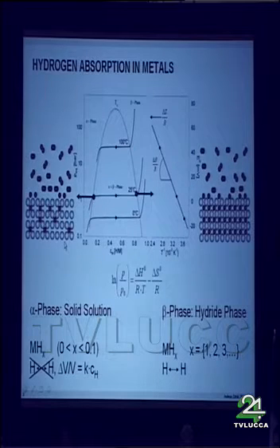And now, due to the volume expansion, we can define that as an active interaction between the hydrogen atoms. We have a phase transition, and above a certain concentration indicated here, we go into this phase transition, and the solid solution phase directly jumps into the hydride phase, and the hydride phase grows through the lattice in an ideal case. Now, this phase transition occurs, of course, only up to a critical temperature indicated here.